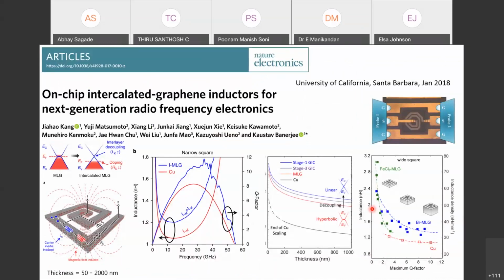If you compare the inductance value of these graphene inductors with the copper, you can see this dotted red line where the maximum inductance obtained is 1.2 nanohenry. But for a graphene inductor, you can get about 2 nanohenry. So this is a scaling graph which shows you cannot make any good copper inductor if you make its thickness below 200 nanometers. And that's why in the previous paper they used a thickness of 1 micrometer. But with graphene, you can have larger and larger inductance with smaller thicknesses, and that is what is called contributing to nanotechnology.